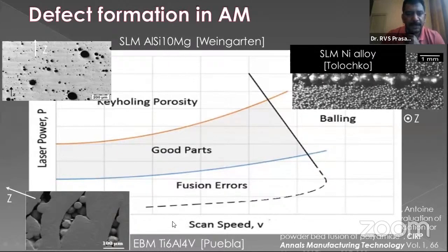So when you have scan speed versus laser power, when the power is very low and at lower scan speeds, you will end up with a lot of defects, as shown in the figure, which are unfused particles or unmelted zones. At the same time, if you have a significant laser power but a very low scan speed, you will end up with gas porosities because of the rapid solidification nature of this process, which has very high cooling rates. Because of that, gases will be generated, and when they try to escape from your liquid pool, they may get trapped in between, and you will end up with gaseous porosity.